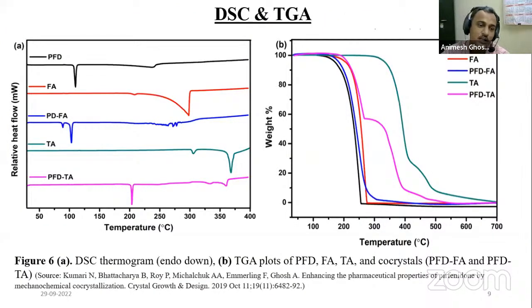If we see, this is the DSC thermogram. Obviously, we know what the DSC thermogram will give. If a co-crystal is genuinely formed, then the peak melting temperature will be different. It will not be similar to either the drug or the coformer. It will be a different one. So if we see here, this is the peak melting temperature of pirfenidone, and this is the peak melting temperature of fumaric acid. But when we have got the co-crystal, that is PFD-FA, PFD mixed with FA, we are getting this. If you see, these are not the same. There is a minimum of 7 to 8 or 9 degree difference, right?